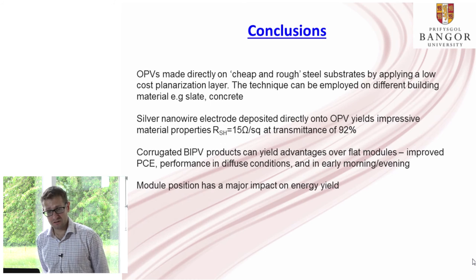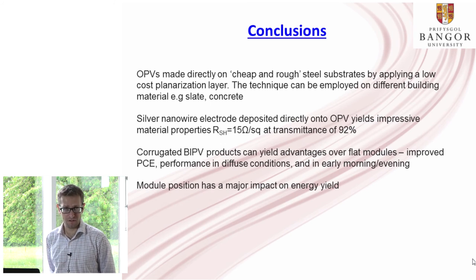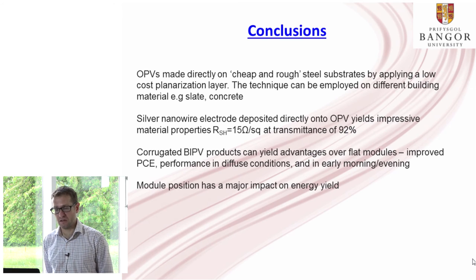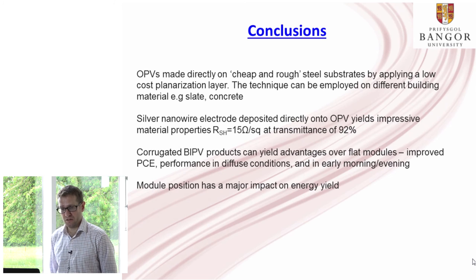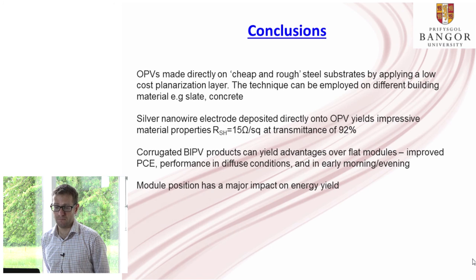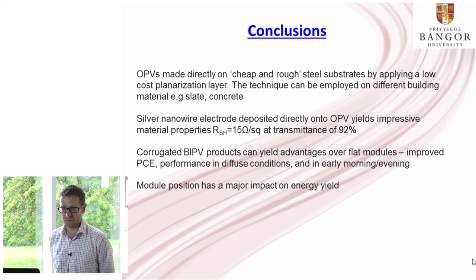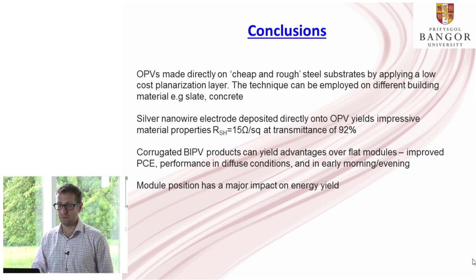So just some conclusions. We've demonstrated that OPVs can be made onto cheap and relatively rough steel substrates using a silver nanowire electrode. We've also demonstrated that OPVs can be used in corrugated building products, and that yields some particular advantages over flat modules. And finally, we've shown that module position has a major impact upon the energy yield.